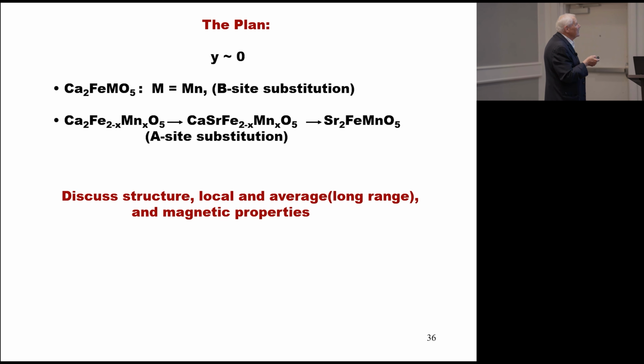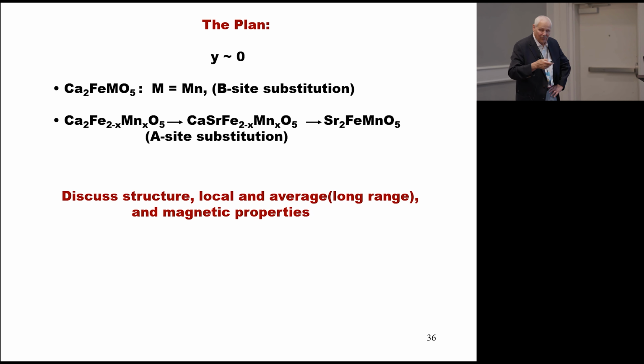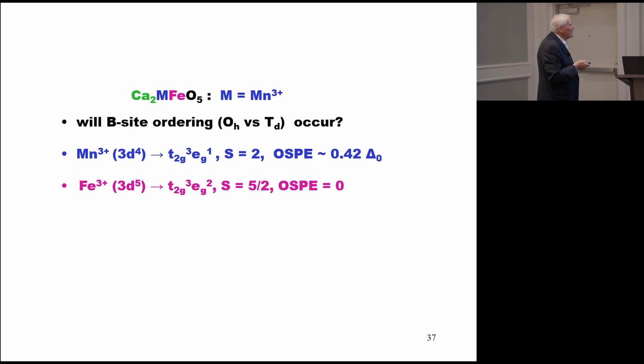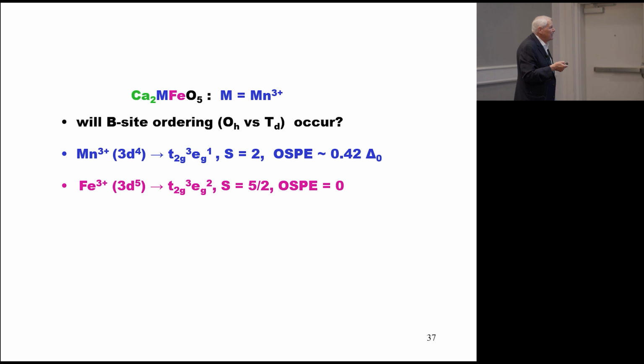Okay, so we're going to look at the all calcium, iron, manganese phase, and two other cases where we substitute 1 strontium for calcium, and then 2 strontiums, to see what happens to the structure and properties. Okay. Now, let's start with this phase, equal amounts of manganese and iron. And of course, we get asked the question, are we going to get B-site ordering? If we work out the octahedral site preference energies for manganese 3+ and iron 3+, it strongly suggests that we'll get strong B-site ordering with manganese in the octahedral site. But how are we going to know this? If you notice, iron and manganese are adjacent elements in the periodic table, right? And so how do we do that?